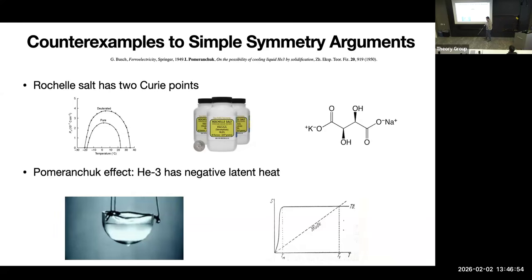The interesting thing is that at first glance, it looks like a usual phase diagram for, say, H2O, for water. But the phase transition here actually has negative latent heat. So it means that if I take an ice cube of solid helium-3 and put it into a hot beverage, instead of cooling down this beverage, it will heat it up. But actually physicists use it in a different way. They put this liquid helium-3 next to the sample that you want to study at very low temperatures. Once you cool it down, it also will absorb energy from the surrounding sample and allows you to reach very low temperatures, around 1 millikelvin. But now cryogenics uses much more sophisticated techniques than this one. So it's quite an interesting phenomenon.